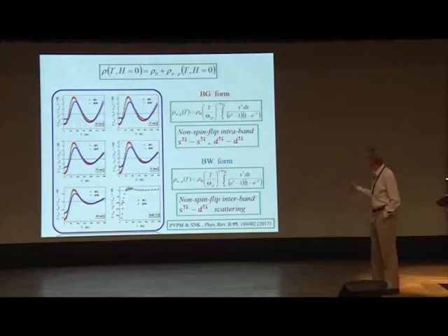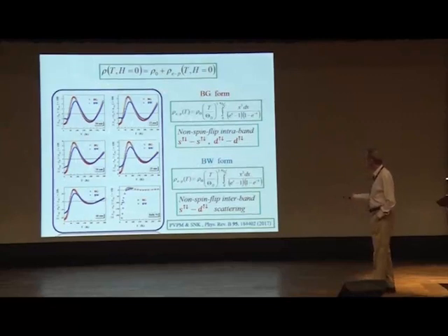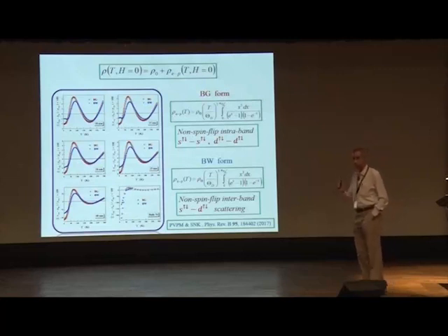That means this functional form, either this or this, does not really describe the observed temperature dependence. This we are doing from 1.8 Kelvin to 300 Kelvin. Okay, but between the two, it looks as if the Bloch-Wilson form fits the data marginally better, but still with systematic deviations, telling that is not really the form.